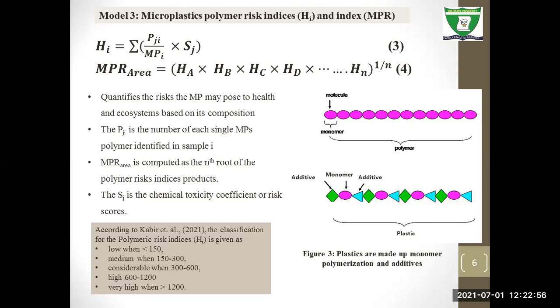So now you have it for a particular sample. To calculate for the entire area, you use equation 4, which is calculated as the nth root of the product of the polymer risk indices of the individual samples. When you get your risk index, according to Kabir et al., the classification is provided here. When it's less than 150, we consider it low. It is medium when it's between 150 and 300. It is considerably polluted when it's between 300 and 600. It's high when it's between 600 and 1200. And it is very high when it's greater than 1200.